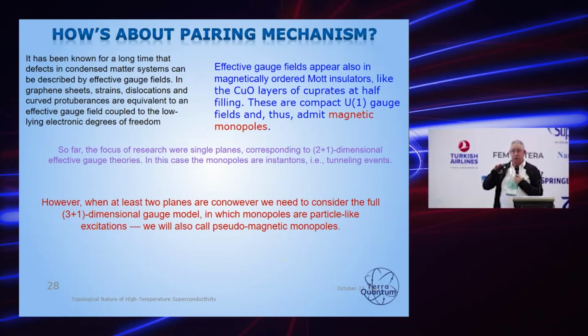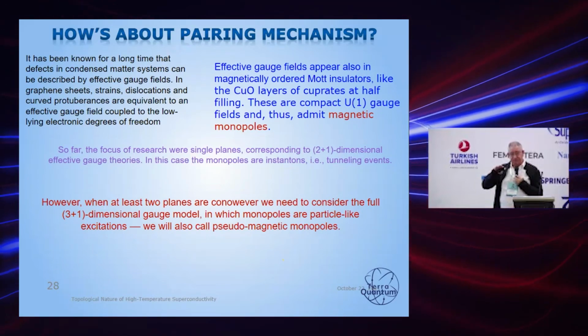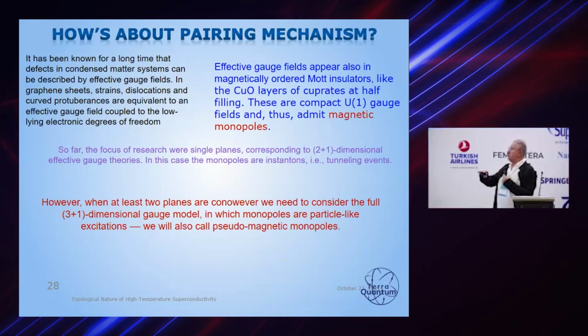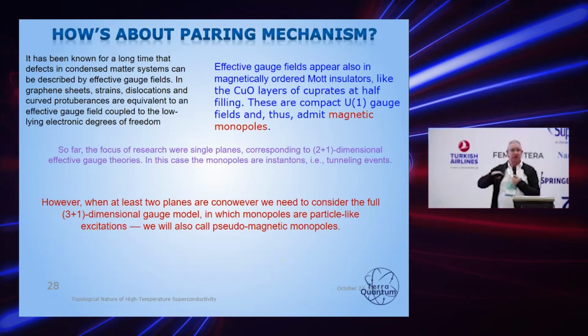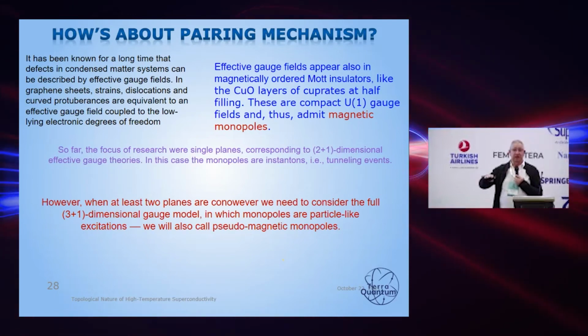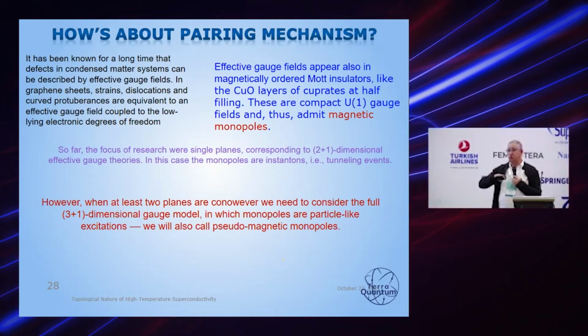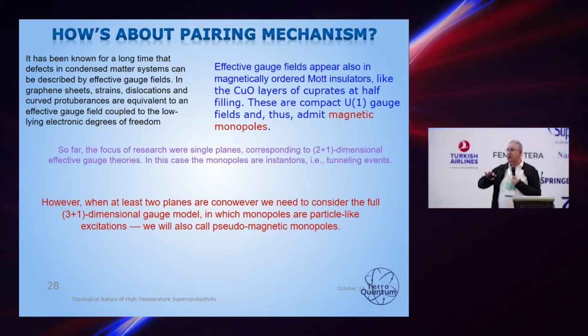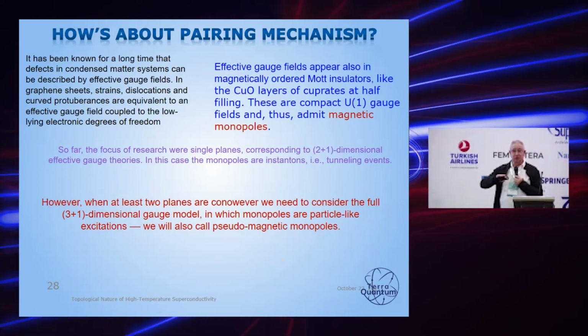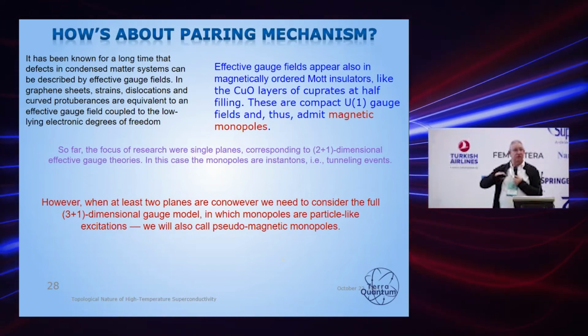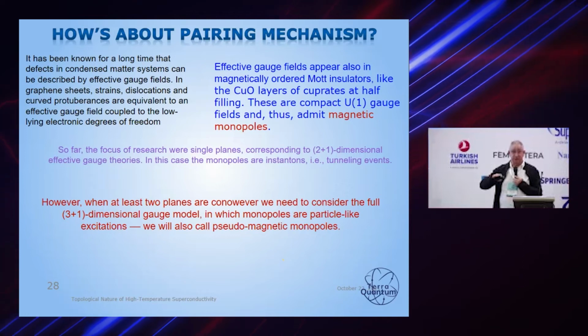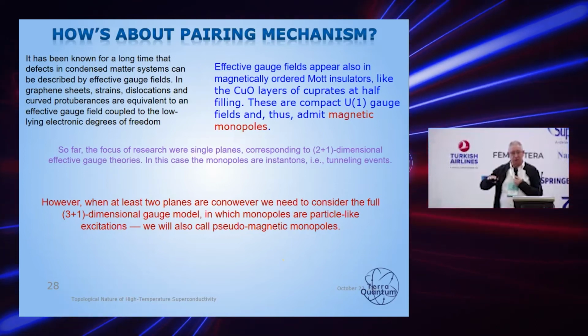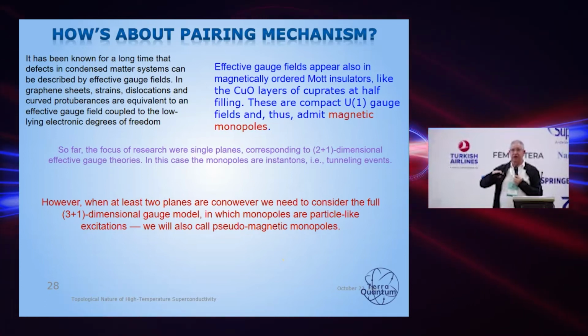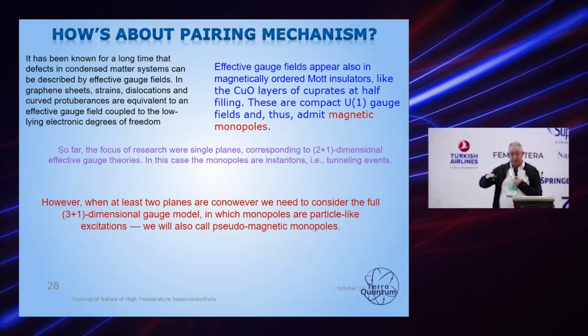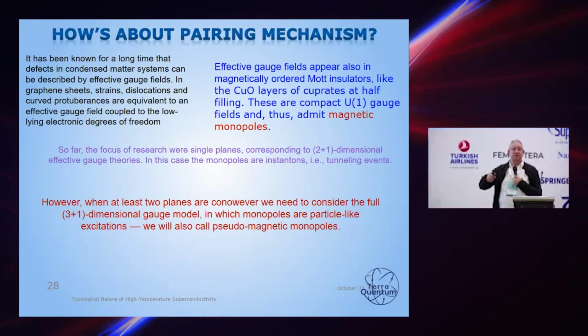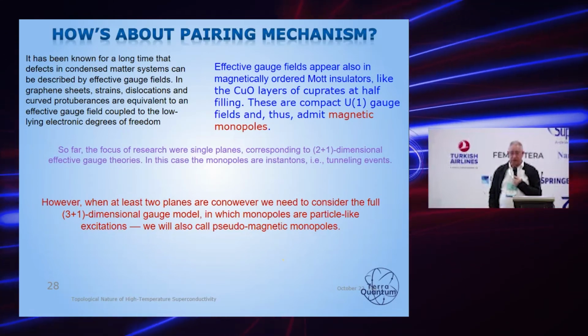You can describe the distortions introduced by the topological defects in the lattice as a curvature. And it was shown in like 100 papers dedicated to graphene that this curvature is equivalent to a pseudomagnetic field. And if you look attentively at what kind of pseudomagnetic field is produced by these topological defects due to this curvature, this is exactly the monopole-like magnetic field.